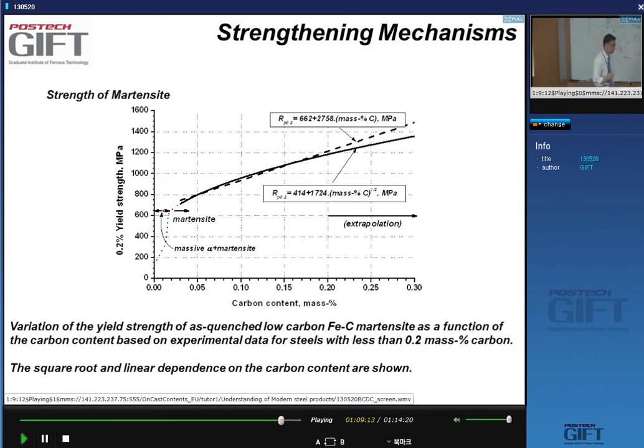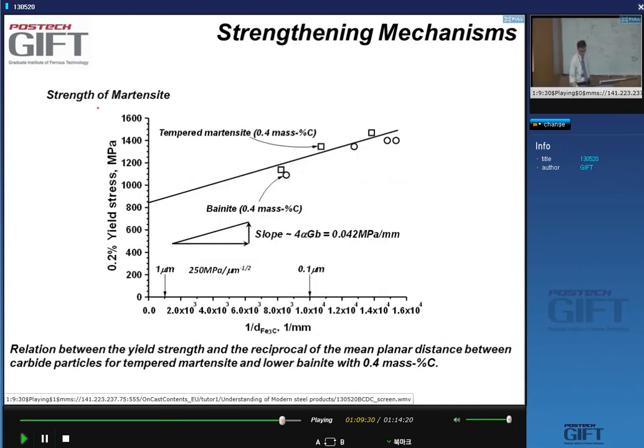So martensite itself is not intrinsically a hard, brittle phase. Yeah? The fact that it's very hard and very brittle and very strong is because of the carbon in solid solution. Martensite sometimes will contain carbide particles when you temper it. Yeah, when you temper it, the carbide particles can contribute to the strength, yes, as carbide particles.